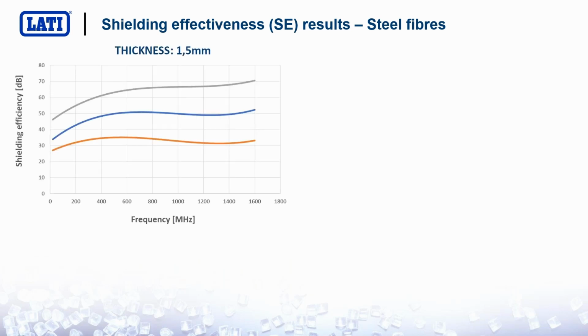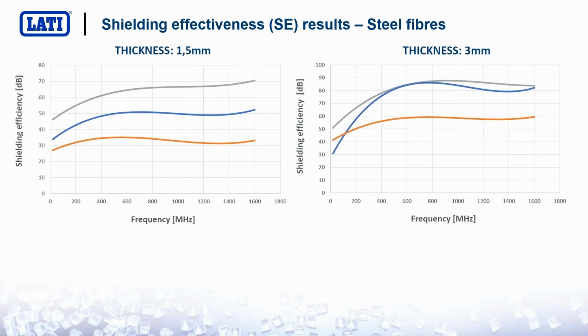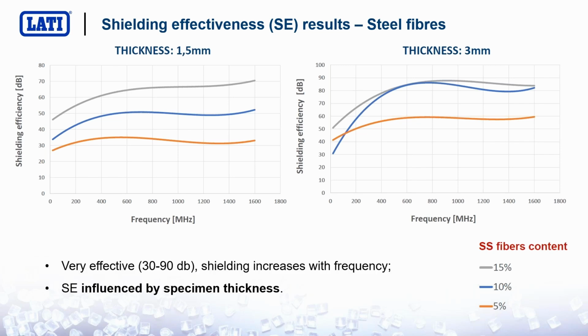First set of results: stainless steel. How does stainless steel perform in shielding effectiveness? These are the results at 1.5 mm and these are the results at 3 mm, changing the stainless steel content from 5 to 10 to 15%. What do we see here? We see that the efficiency grows with thickness, going from a maximum of 70 to a maximum of 90 dBs. And we also see that the shielding effectiveness is influenced by the frequency of the incoming signal.